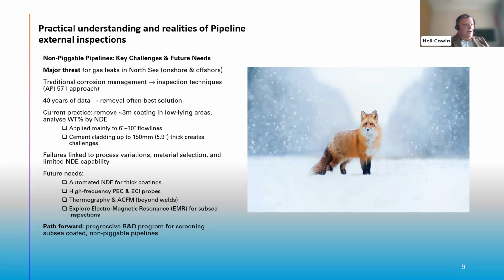Right now, we're sitting at about 250 meters, which is why Petrobras and Exxon do tend to pick up some of their flexibles and bring them topside to have them re-inspected onshore. They do that on a set frequency because of fatigue. They can only inspect so much of it in water up to 150 meters, and after that, deep water flexibles are generally problematic to inspect. So cost-wise, it depends on the equipment, but I would plump for Pulsed Eddy Current or ACFM as my two favorites. Great, thank you, Neil.